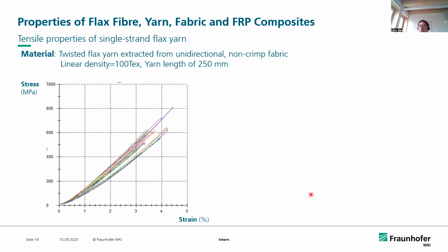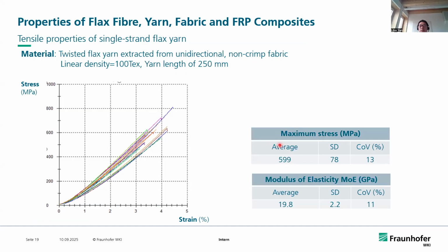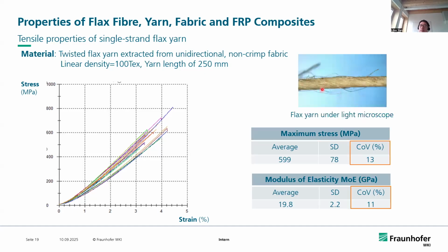Next, let's move on to the flax yarn. The flax yarns are also extracted from the same fabric. As you can see, the average tensile strength is about 600 megapascal. There was a significant reduction from the 800 to 1000 for the single fiber. And also there was a significant reduction in the modulus of elasticity compared with the single fiber. But what is interesting is the reduction in the coefficient of variation, from the 20 to 50% of the single fiber, dropped to 11 to 13%. What does that mean? When we twist the short fibers into yarn, we are able to reduce the variation and make the properties much more predictable.